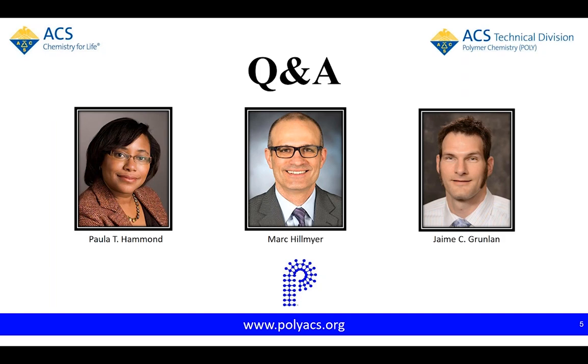I know that I can bring Paula into this discussion because I know she's worked on drug delivery with pH response. And so, of course, some of that pH response is disassembling the film. In that case, for drug delivery, it's a good thing. You want it to disassemble. So it just depends what you're after. If you don't want something to disassemble, you would certainly cross-link it. If you use strong polyelectrolytes, it's also much more resistant to pH than a weak polyelectrolyte. But all of this depends on the exact chemistry you're using and what exact pH level you're talking about.